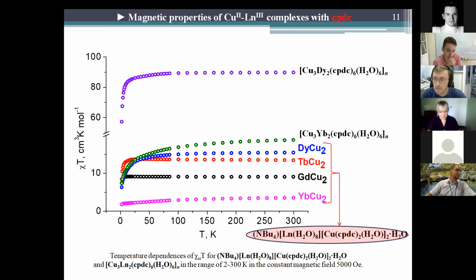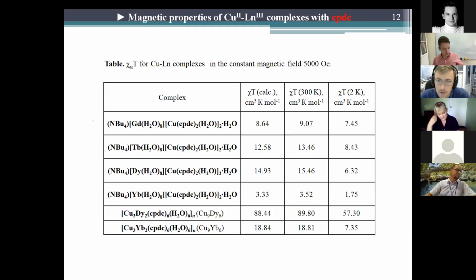And then for terbium and gadolinium complexes, the values demonstrate a sharp drop up to a minimum value at 2 Kelvin. For dysprosium, χT smoothly decreases with decreasing temperature. This appeared due to the presence of weak antiferromagnetic interactions between metal ions and their combination. The experimental values of χT at 300 Kelvin are in satisfactory agreement with the theoretical values for isolated ions.